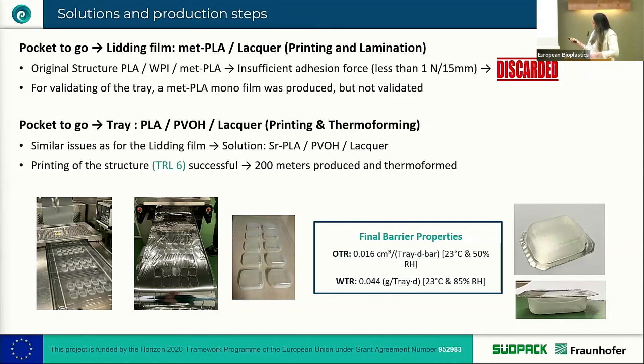Afterwards, we successfully did this, and as you can see here, we produced the packaging with thermoform, and after thermoforming, we actually reach good final barrier properties. Also, my colleague Steven already told you that this packaging is biodegradable and was tested successfully.